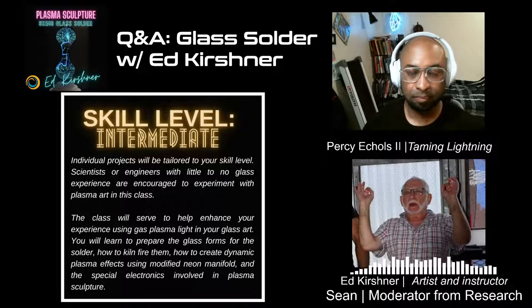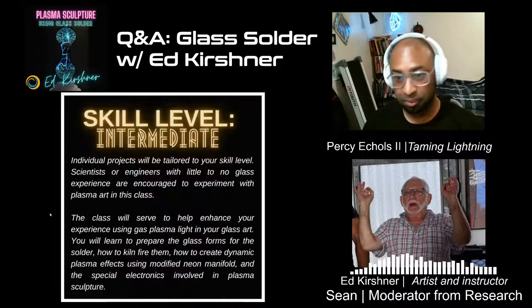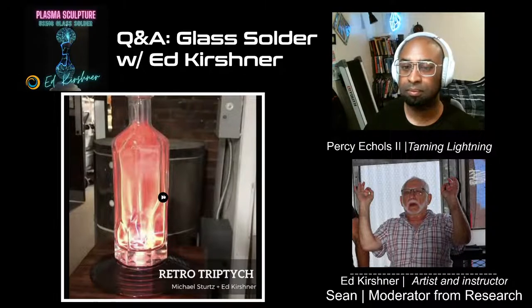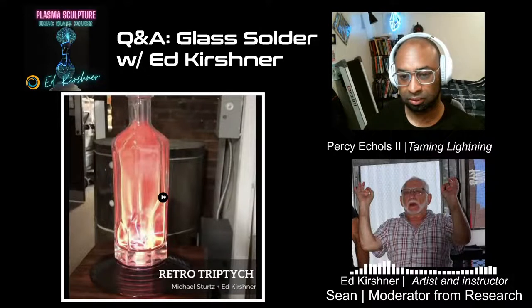The other is a weird one. That bottle that Percy had up there was a whiskey bottle, and with much manufactured glass, it took me a long time to figure this out: the glass becomes conductive after it's been fired a few times. I could not understand that. So you don't want to do a plasma piece where the glass is conductive, where you go near it and get a shock. In effect, the glass turned to metal, even though it didn't look any different. Wow.